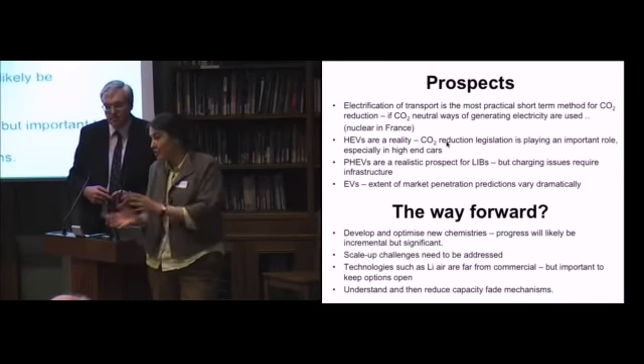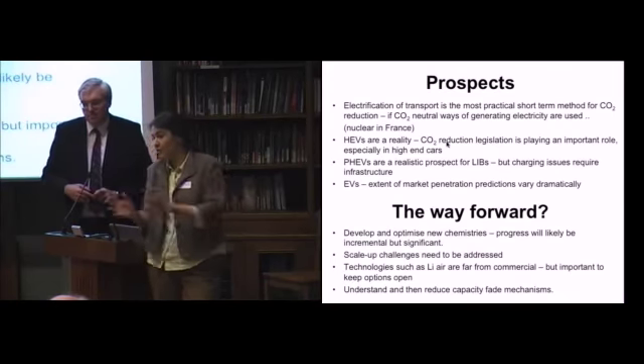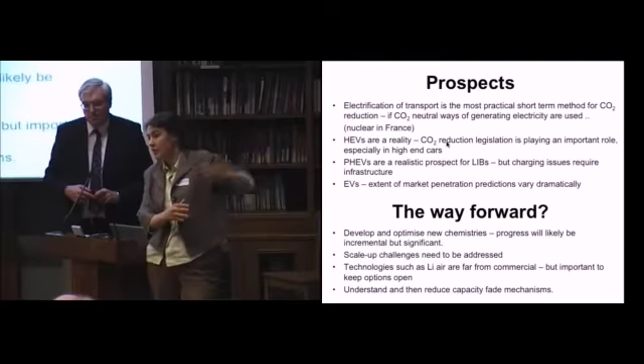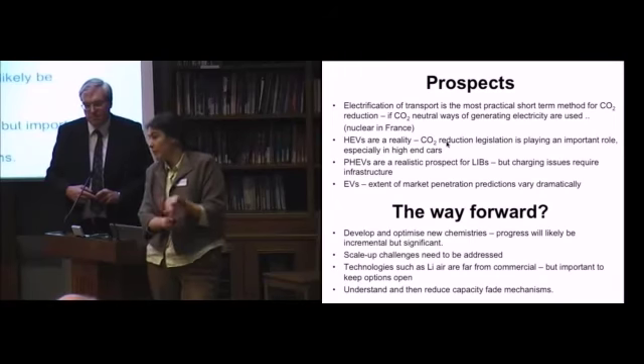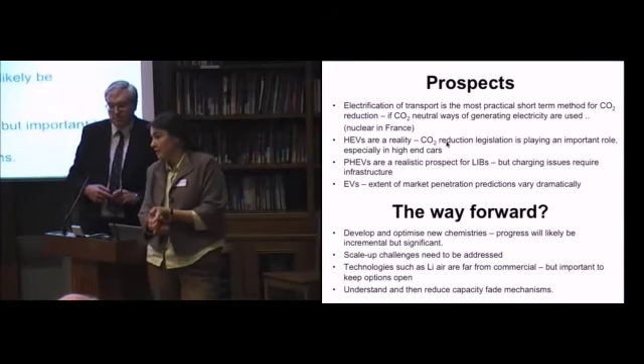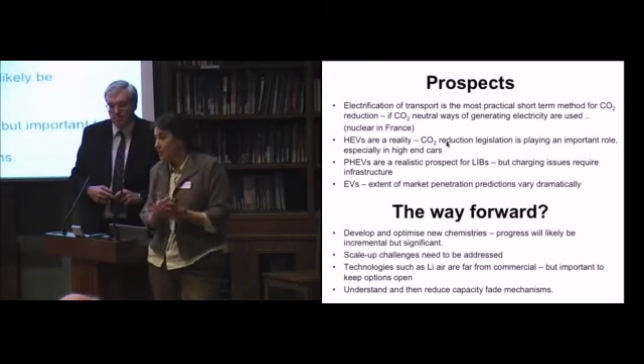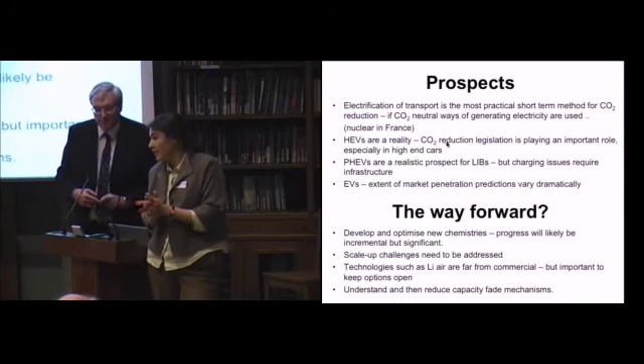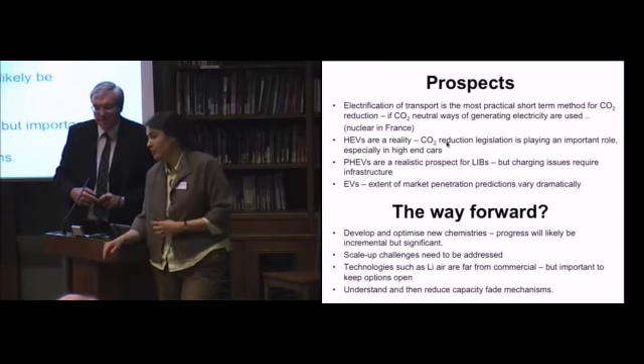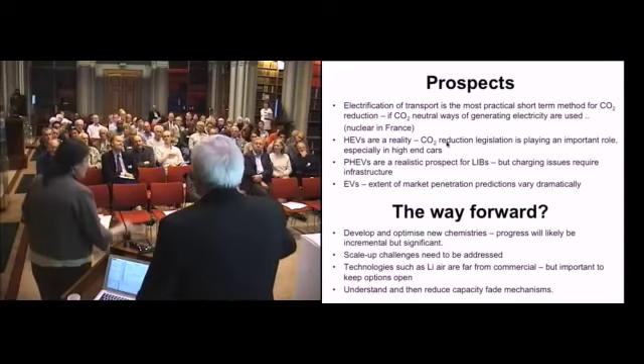But remember, when you charge fast, it's not just the anode, it's also the cathode. Because if you charge too fast and you get overcharging on the cathode side, then you're back in safety issues. But lithium iron phosphate is a fast material. Lithium manganate is a fast-charge material. Unfortunately, lithium manganate has issues of dissolution, so I doubt that 20 years number based on the cathode. The titanate may survive, but the cathode is going to be your problem. So it's certainly a material that's being considered.